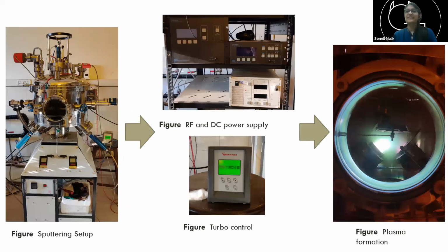Okay, so a little bit about the lab. These are pictures, all of them from the ultra low temperature lab at IISER Mohali. This is the sputtering setup. This is the impedance matching for the RF system. This is the RF power supply. This is the DC power supply. This is the turbo control. The turbo is a turbomolecular pump, which allows you to achieve very high vacuums of the order of 10 to the power -6 torr or -7 torr. And this here is plasma. So yay, sometimes the lab is pretty.